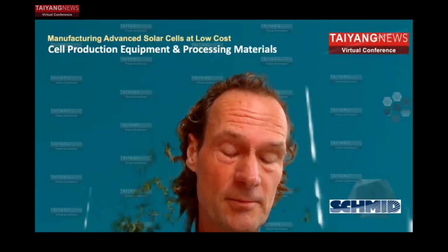Well, cleaning, I think that's a very good point, Shravan. Cleaning is more and more crucial as we go to higher efficiency. Heterojunction surfaces are extremely sensitive to contamination, so here cleanliness is even more important than for TOPCon. But I would also claim that cleanliness for TOPCon is definitely very important and plays a major role in future efficiency increases. This is clear, and this is what we have taken care of in our systems, so that we have reduced the particles down to zero. We developed special transport systems to not contaminate the system. And of course, the cleaning in the system, which involves ozone cleaning, also contributes to cleaner surfaces.